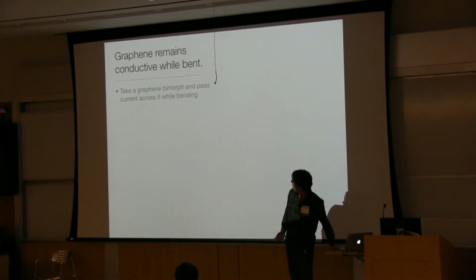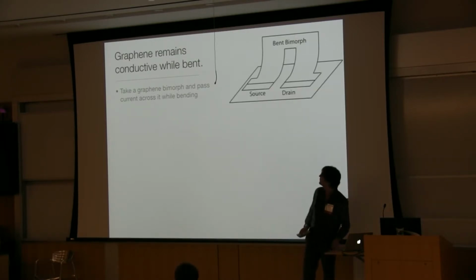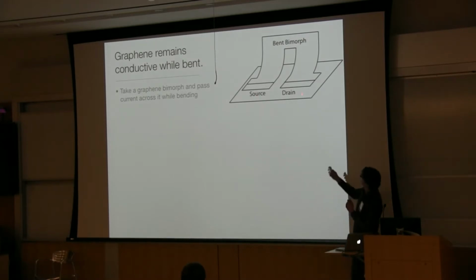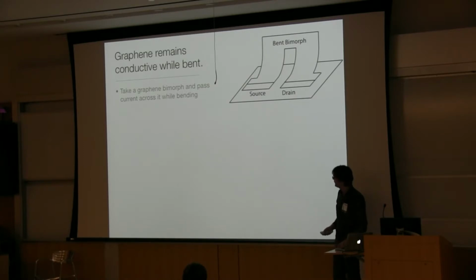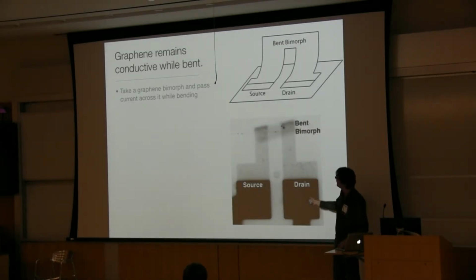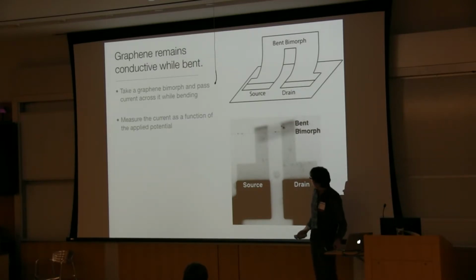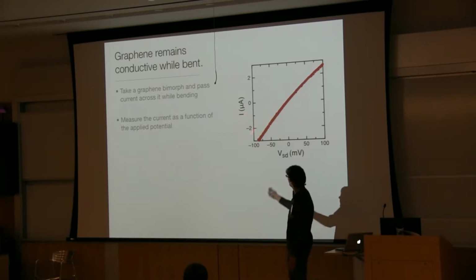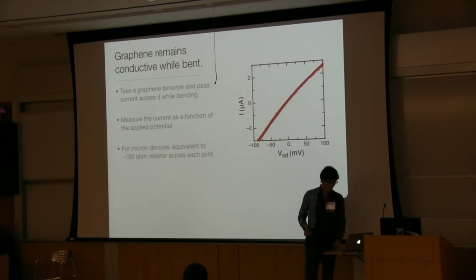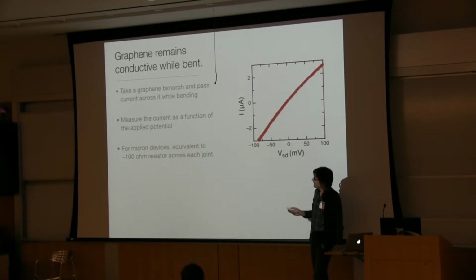The experiment here is pretty simple. You take a graphene bimorph, and you want to pass a current across it while it's bending, and see what it does. So this is what we built. It's a source, a drain, and then the current passes through the bent bimorph, so you can measure how much current flows as a function of voltage. Here's the actual experiment. You can see source, drain. This fuzzy image in here is the bimorph bending out of the plane. When you pass current across it, you can measure the current that flows as a function of voltage, and from there you can measure the effective resistance along this joint. What's interesting is that if you extrapolate from these measurements, you would find that if you built a micron-sized device, each joint would be equivalent to about a 100 ohm resistor.